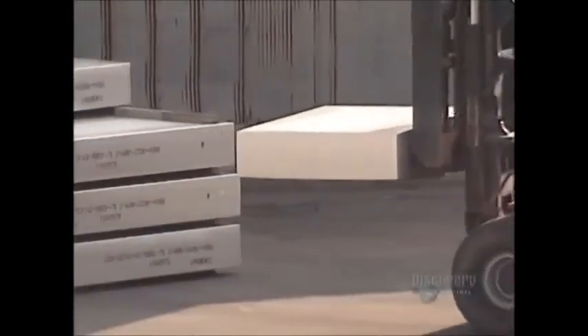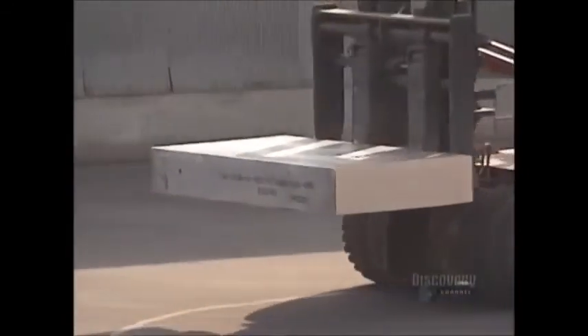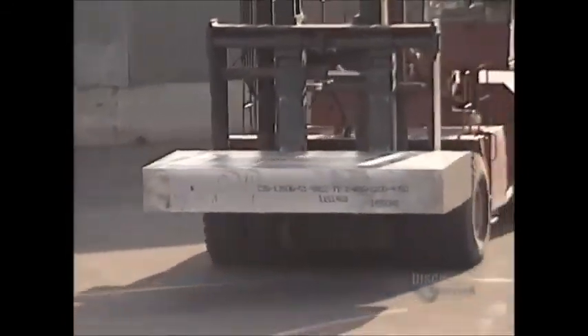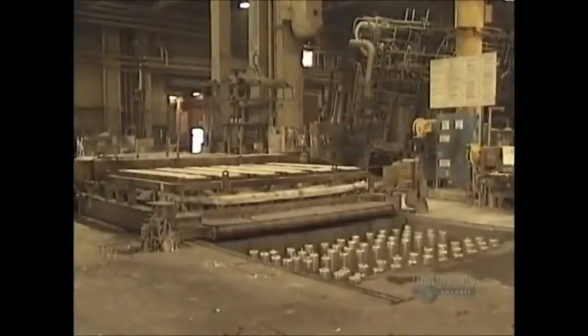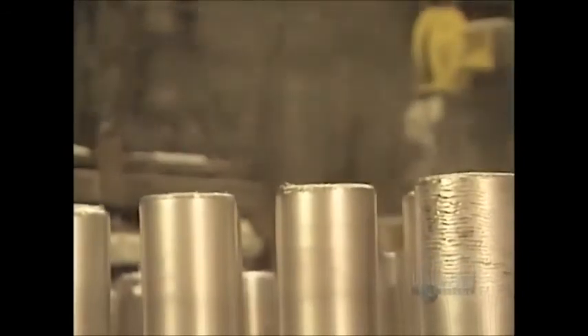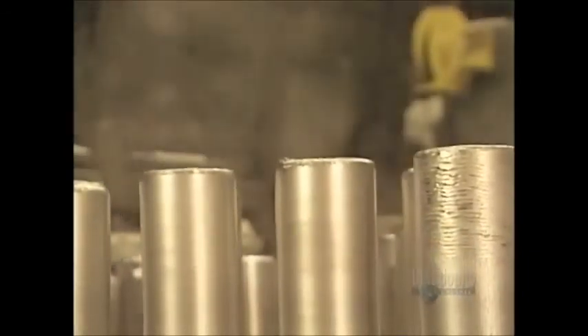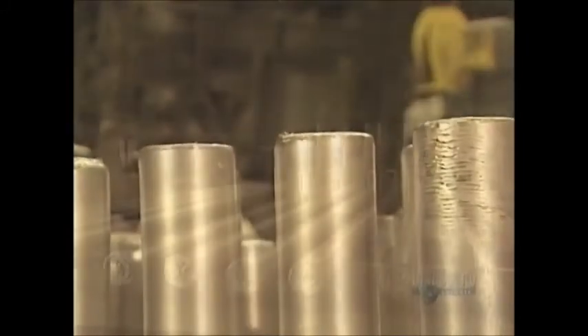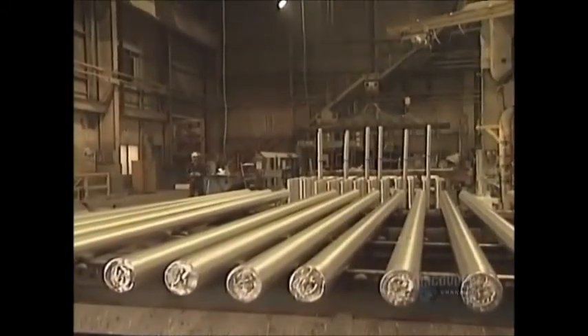The cooling of aluminum pieces is accelerated by water sprays. The large rectangular ingots, which can weigh up to 25 tons, will head for hot rolling, eventually leading to fabrication of products such as aluminum foil. From 4 to 5 tons of bauxite have produced 2 tons of alumina, which in turn produces 1 ton of aluminum. This particular plant produces 200,000 tons of aluminum annually, yet some other facilities can turn out as much as 400,000 tons.